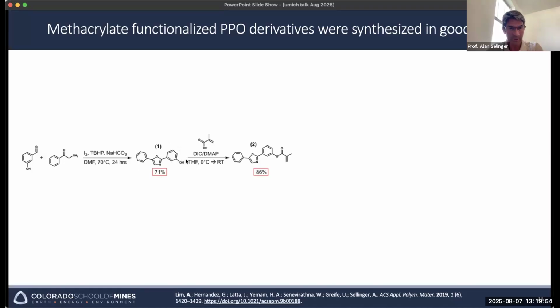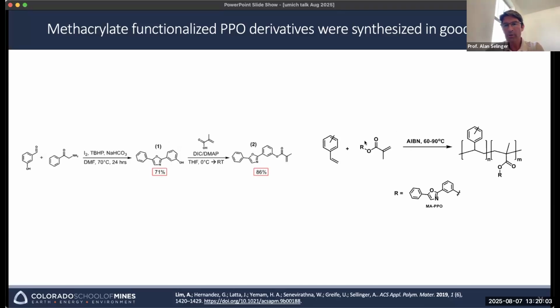That hydroxyl group can be reacted to put what's called a methacrylate. That methacrylate can then be co-reacted into the matrix. And so here's polystyrene, here is this methacrylate functionalized dopant. This can be added in, heated, and then be chemically incorporated into the polymer.